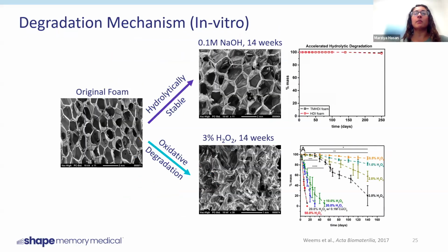And so for the last couple of slides, I'm going to talk a bit about the biocompatibility and the degradation of our material. I mentioned our material is biodegradable, and we've done some work to assess in what mediums this material is biodegradable. So hydrolytically, our material is stable. We don't see any mass loss after 14 weeks in sodium hydroxide, though we did discover that this material is oxidatively degradable.